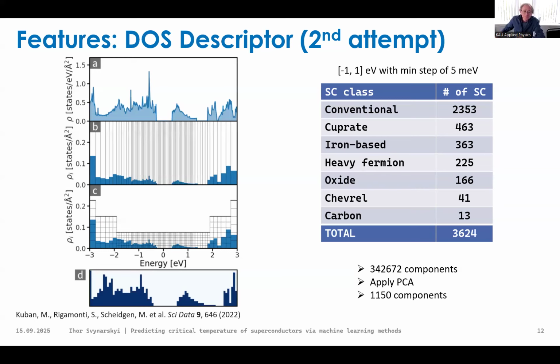Good talk. Physically, for the low TC compounds the lattice is definitely important, because it's phonon-driven superconductivity. Somehow that information is lacking from everything you considered, right? Even the atomic number is probably not in. Intuitively, if you want to improve for conventional superconductors, at least some information on phonons, lattice vibrations or electron-phonon coupling should flow into the model.